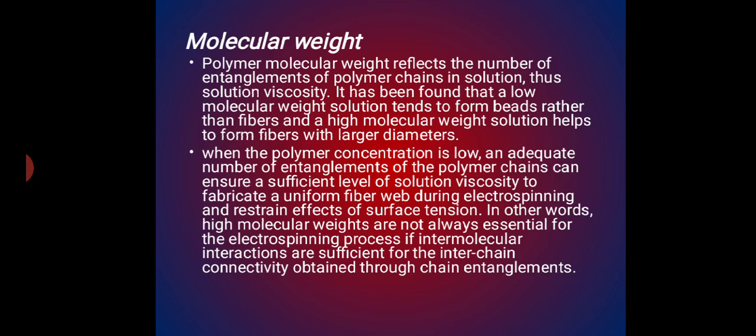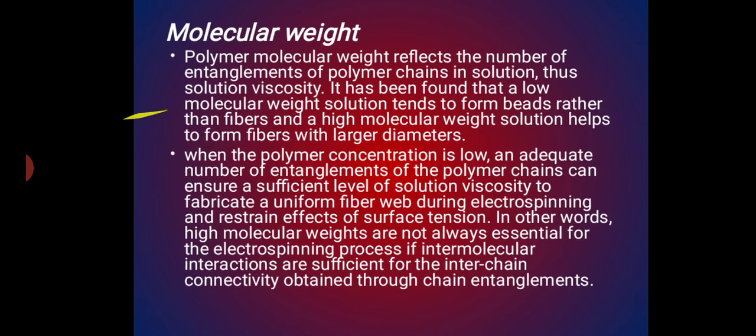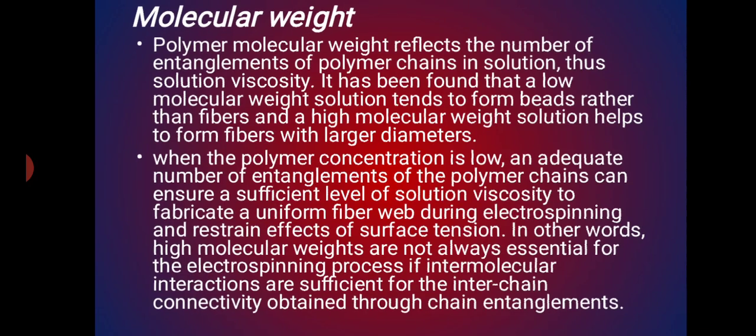Again, the molecular weight. The polymer molecular weight reflects the number of entanglements of polymer chains in solution. Thus, in terms of solution viscosity, it has been found that a lower molecular weight solution tends to form beads rather than fibers, and a higher molecular weight solution helps to form fibers with larger diameters.